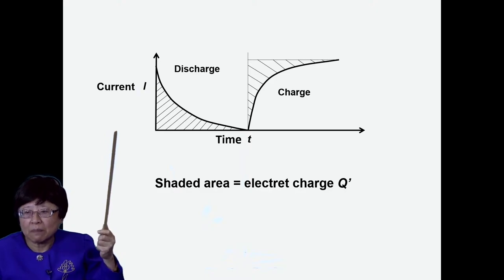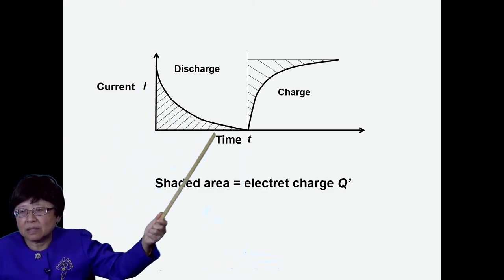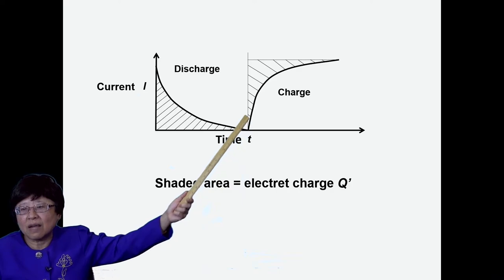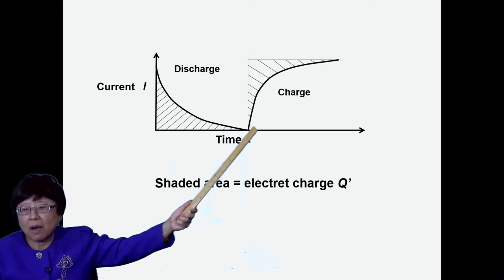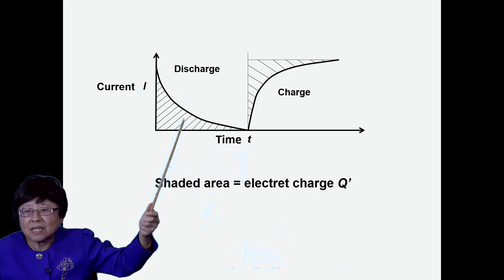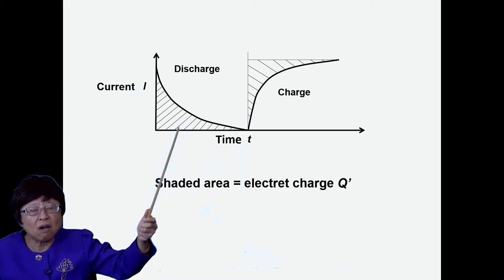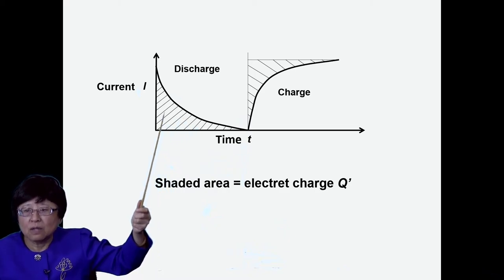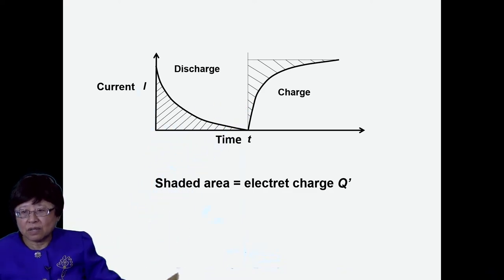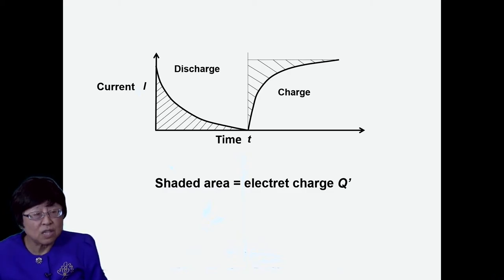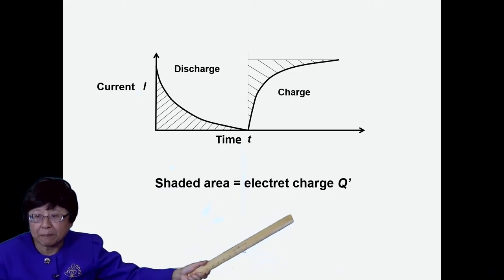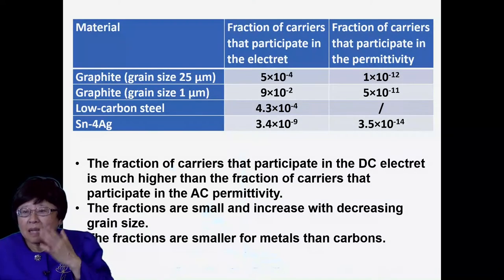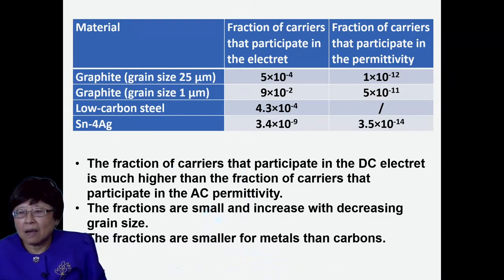Now, we can analyze the discharge-charge curve by recognizing that the current, which can be obtained from the voltage by using Ohm's law, would decrease to zero during discharge and then rise, restored upon charging afterward. And you can integrate the current versus time to get the charge involved during discharge and during charge. The shaded area is the charge associated with the electret. I call that Q prime. Here shows the result of that integration.